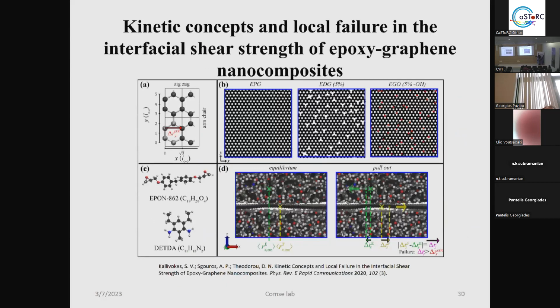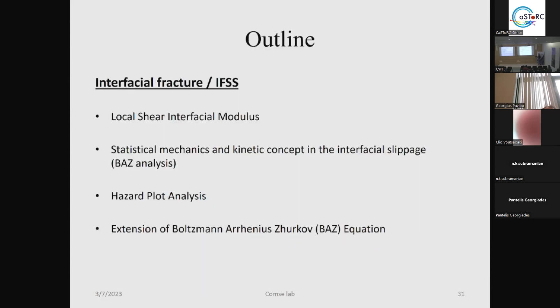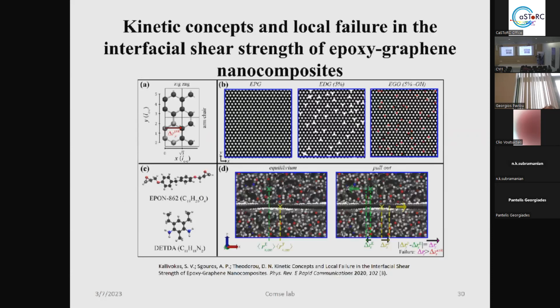After that, we took these epoxy networks and we filled them with graphenes in order to have nanocomposites. We filled them with three different types of graphene. Pristine graphene that you can see here, the ideal graphene, let's say, so EPG, the epoxy pristine graphene. The epoxy stands for the polymer matrix. EDG, with defective graphene with holes randomly in the space with 5% atomic fraction due to the holes. And EGO, epoxy graphene oxide, again with 5% atomic fraction, and again randomly spread into the space of graphene.